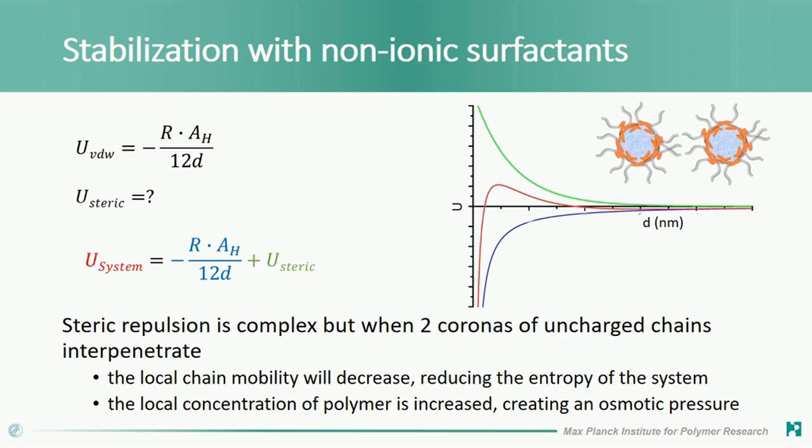If you pack the chains too much, they are not as well solvated. They cannot reach their thermodynamically most stable conformation, which is defined by the radius of gyration of the free chain. And if it's confined, if it feels this effect of confinement, you slowly lose any enthalpic gain that you could have by not interdigitating.